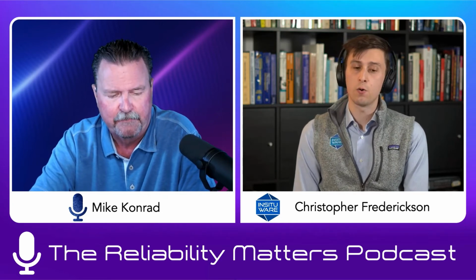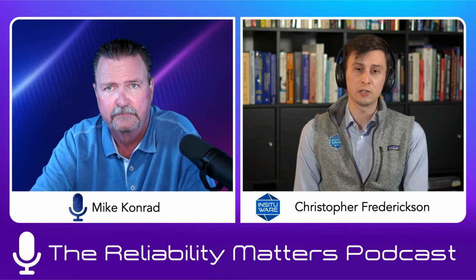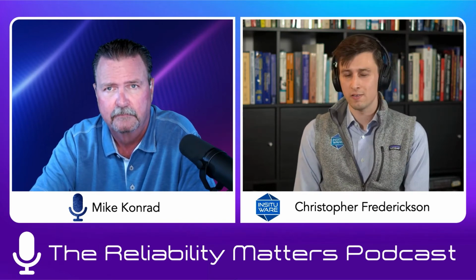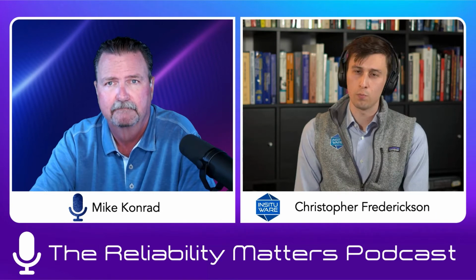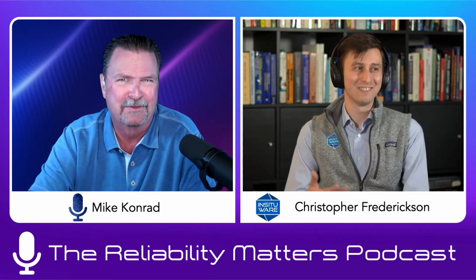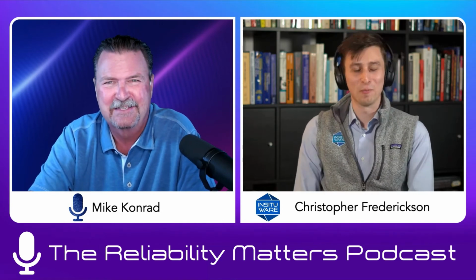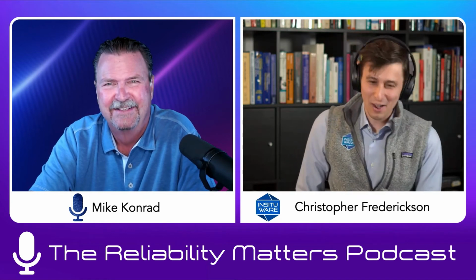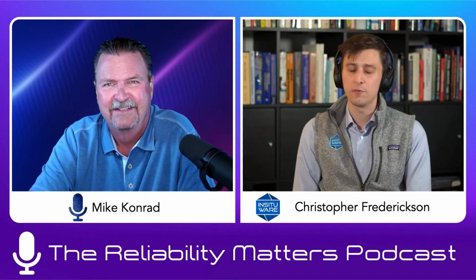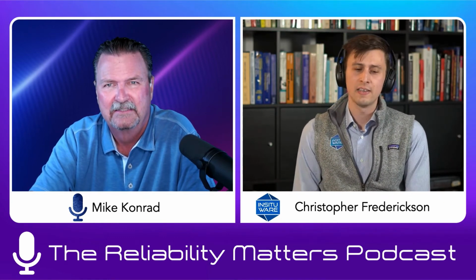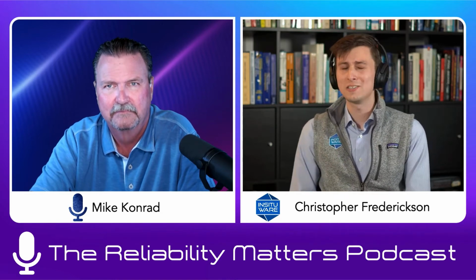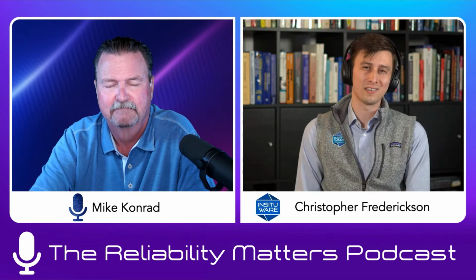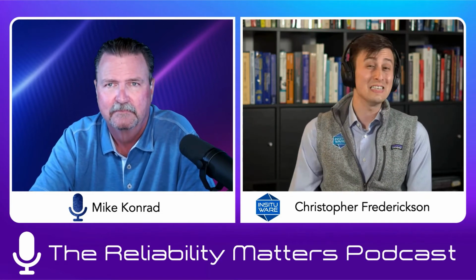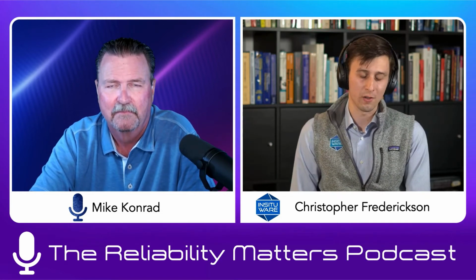Yep, exactly. As an example, for conformal coating measurements, it's a little bit difficult because the coating cures onto the probe. Right, it conformally coats the probe, doesn't it? Yes, it does conformally coat the probe. So in that case, it doesn't end up being reusable. Solder paste, you can reuse it quite a lot without any problems. The only issue is that some very active solder paste will start to eat away at the surface much more quickly than others. Sure.